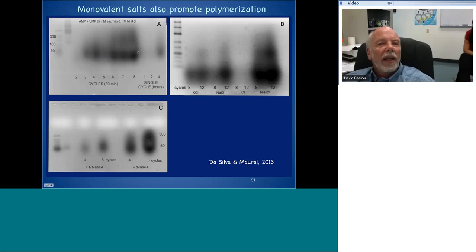What you'll see here is we have apparently 2 kinds of RNA being produced. We got this down here in the 20 to 30 mer range. We have the stuff up here, much longer, way up into the 300 mer range. It does take cycling, because if you look over here to the right, this is a 4-hour single cycle. That's the same amount of time as this 8 cycles of half an hour each. So you can see the cycling really does help whatever it's doing.